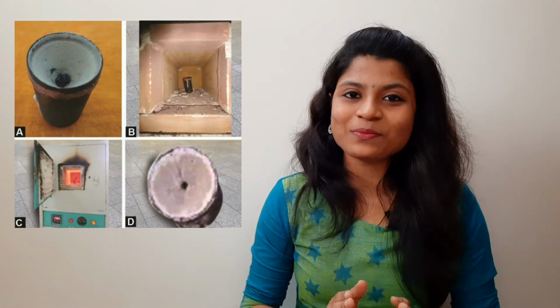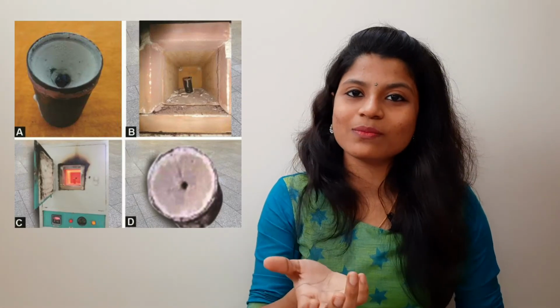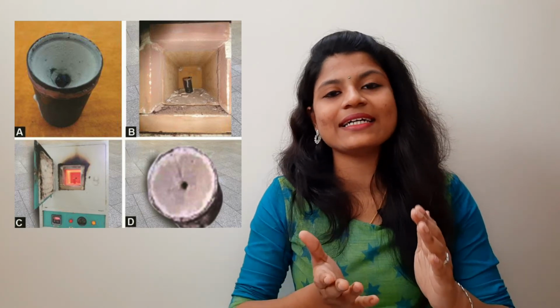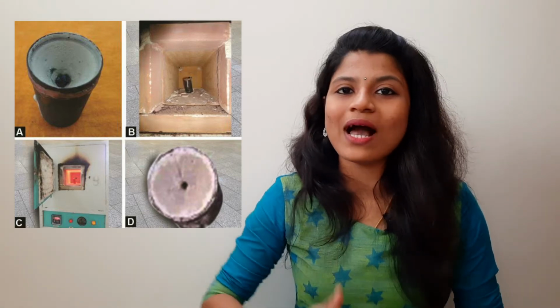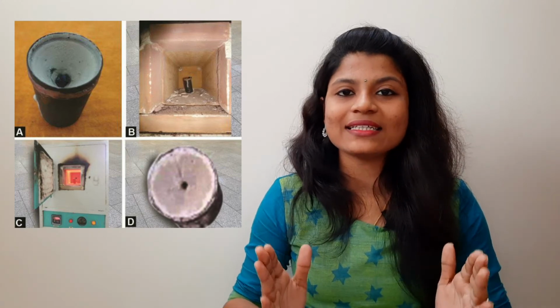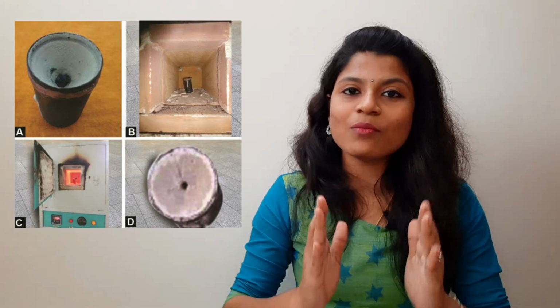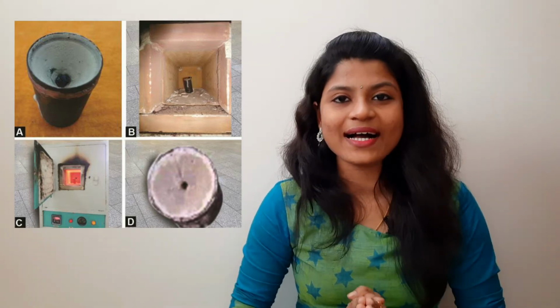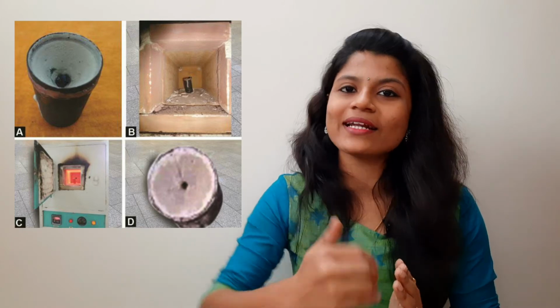The investing material is mixed by the vacuum mix technique to avoid air bubbles and entrapment of gases and oxides. Once the investment has set for 1 hour, it is ready for burnout. The crucible former is removed carefully and the investment is set for burnout. Burnout is nothing but wax elimination by heating the investment in a thermostatically controlled furnace until all traces of wax are evaporated.